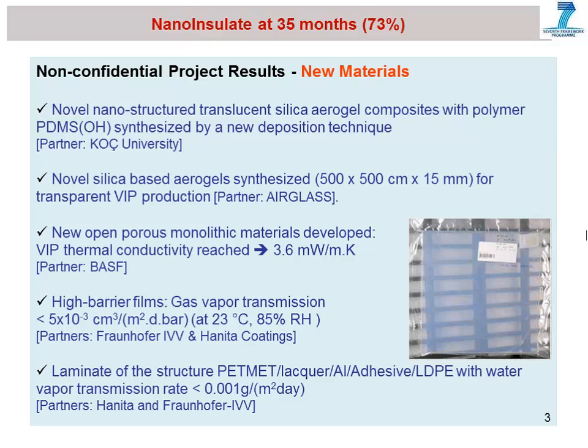High barrier films have been developed where the gas vapor transmission is less than 5 times 10 to the minus 3. And this is developed between Fraunhofer and Hanita Coatings. And the importance of that is obviously increasing the lifetime of the product. If you have very low vapor and gas transmission, then you obviously can increase, based on the curve that Daniel showed earlier, you can increase the lifetime of these products quite dramatically. And we have a laminate of the structure, polyethylene terephthalate, metallized film, lacquer, aluminium layer, adhesive, LDPE, with very low water vapor transmission rates. That's also between Fraunhofer and Hanita.